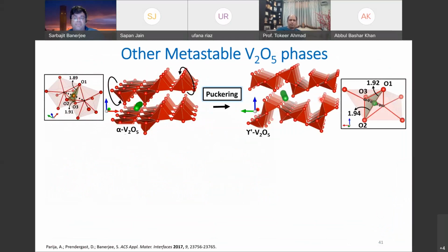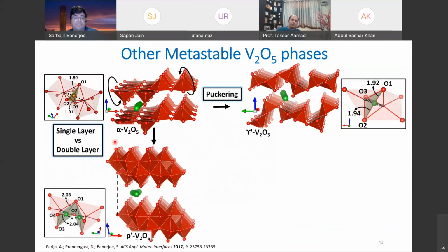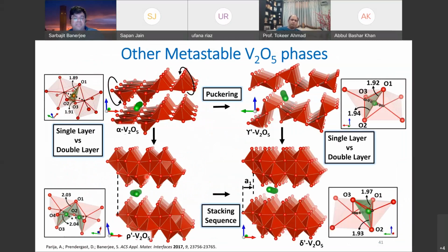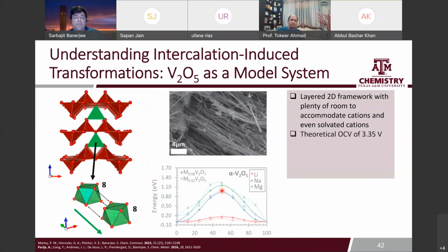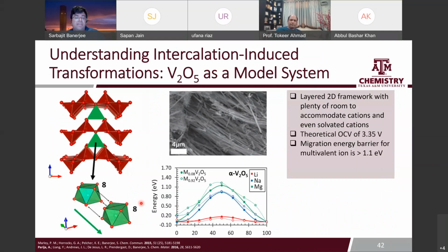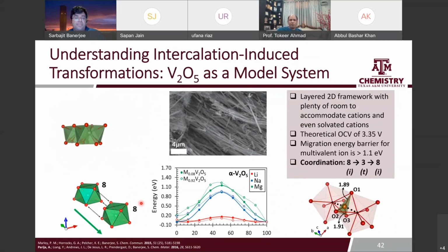We can access this puckered phase through the insertion of lithium and then de-insertion. And this is a gamma prime phase, or we have also double layered these rho phases and delta phases that we can get. And then these two phases are related to each other based on how the layers stack. And through accessing these different phases, we can change the precise pathways that the ions adopt through the lattice. Okay, and so the problem with alpha V2O5, like I talked about yesterday, is that the diffusion path for ions through this lattice is from 8 coordinate to 3 coordinate to 8 coordinate, right? So this is a very large change in coordination environment, and it's essentially impossible for magnesium to go through this. So alpha V2O5, at least at room temperature, is not a very good host for this.